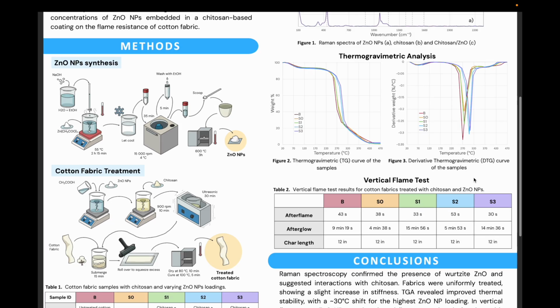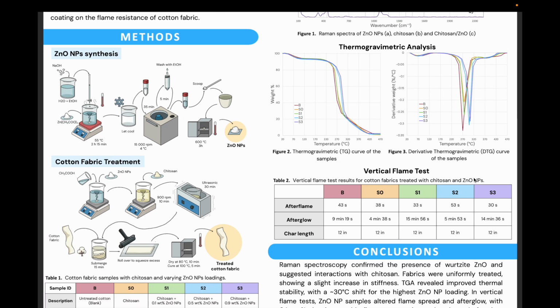And for the flame tests, all fabrics were ultimately consumed. However, the flame behavior strongly depended on zinc oxide content. The sample with 0.1 weight% zinc oxide showed the longest afterglow, lasting about 15 minutes and 56 seconds, and a partial suppression of the flame compared with the blank and chitosan-only samples.